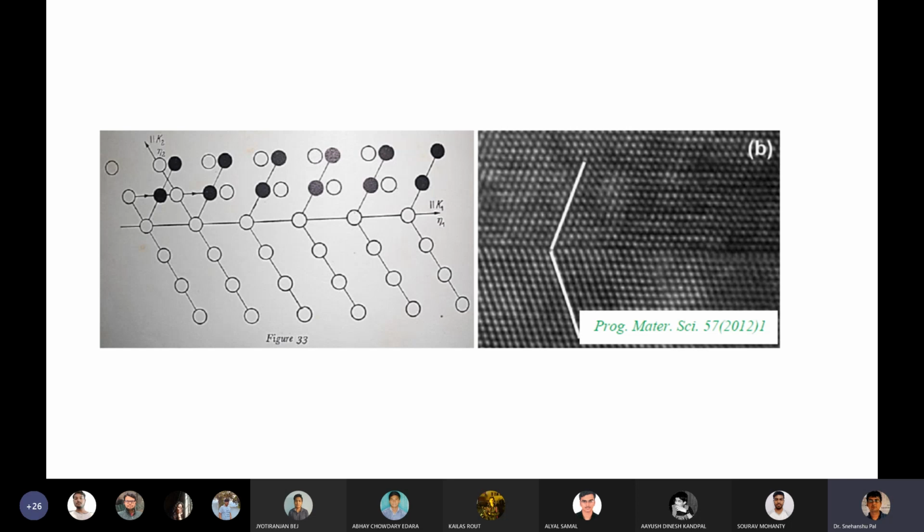What kind of materials? Suppose HCP metals, cross-slip depressed metals, low stacking fault energy metals. Having cross-slip depressed, they are not going to have a freely operative cross-slip mechanism. And BCC metals, which are not so dislocation glide friendly in crystal structure.